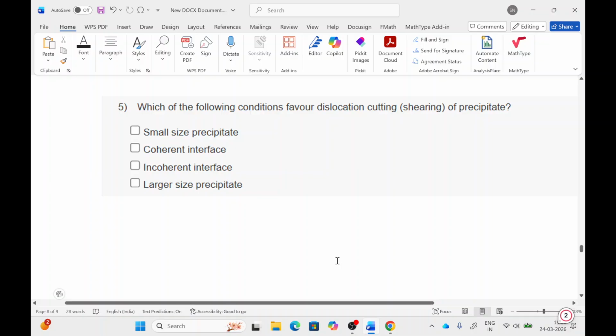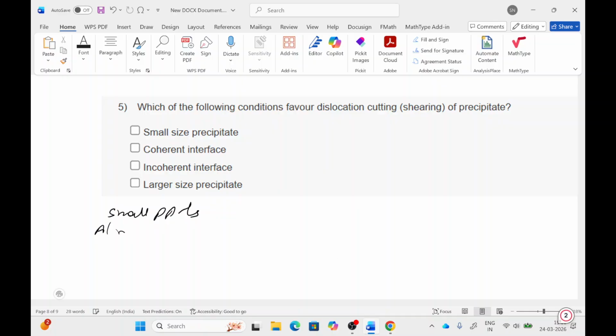With increasing the size of the precipitate, the interface also changes. For small particles, so small precipitates, the interface between the aluminum matrix and precipitate is coherent. Coherent means atom to atom matching.